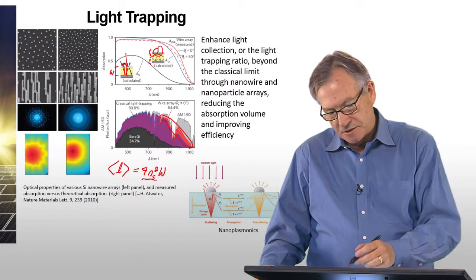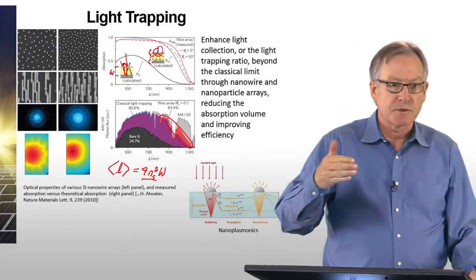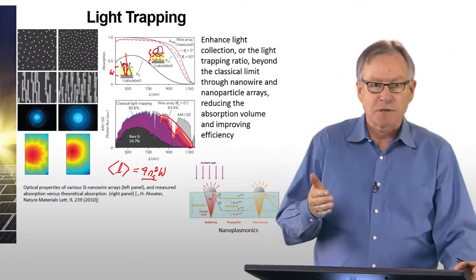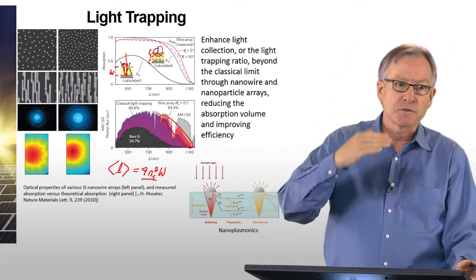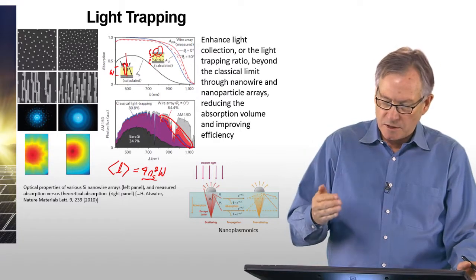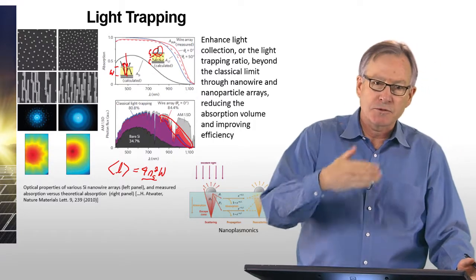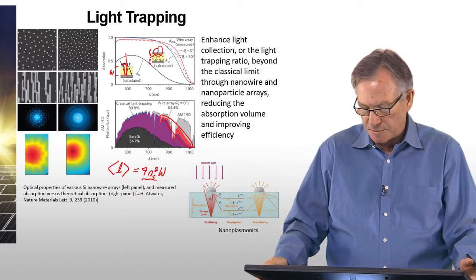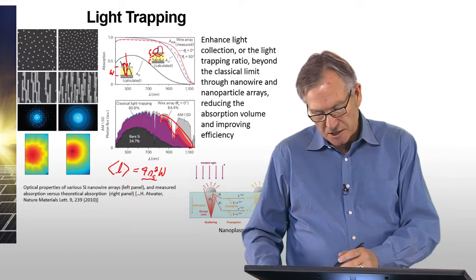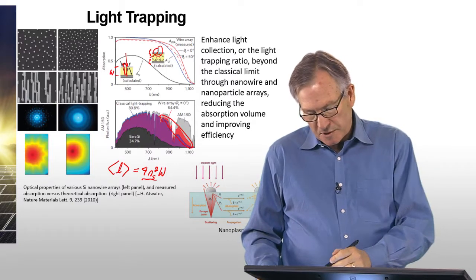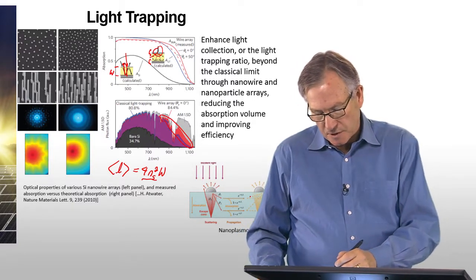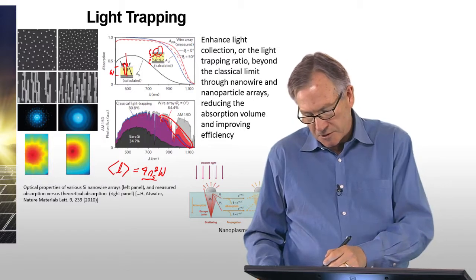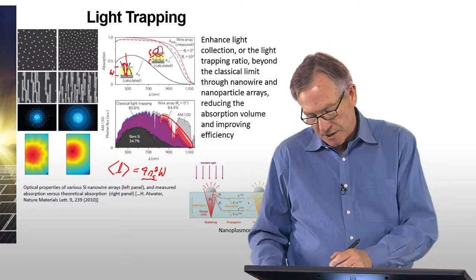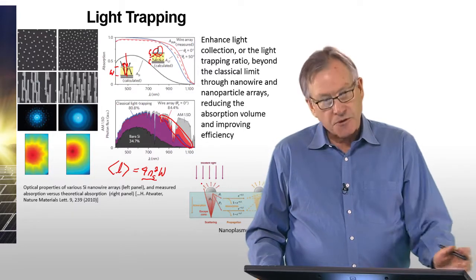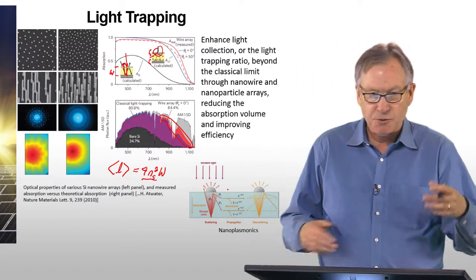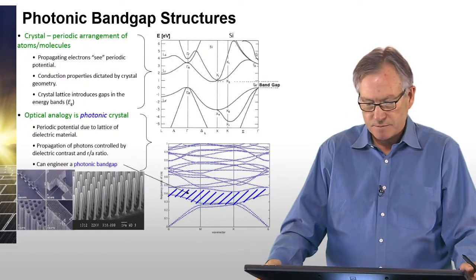The extra red shown here is an enhancement that they measured which goes beyond the classical light trapping limit, demonstrating that a nanostructured type of surface can give you an increased path length or trapping that's beyond the classical limit. This can also be realized using nanoplasmonic systems, in which an array of metallic scatterers leads to the formation of surface polariton modes, modes that form parallel to the surface and also lead to light trapping. So there's also a lot of work on the nanoplasmonic approaches.